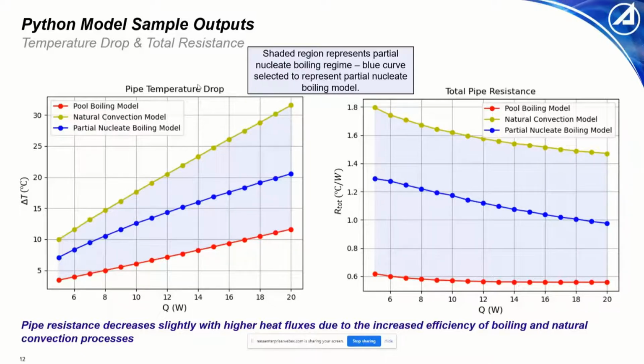One thing that is important to note is that our pipe resistance actually decreases with higher heat fluxes. The reasoning for that is that the efficiency of boiling and natural convection increases as the heat flux increases as well.